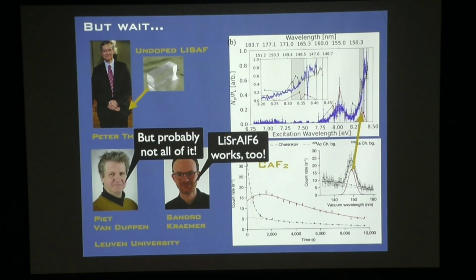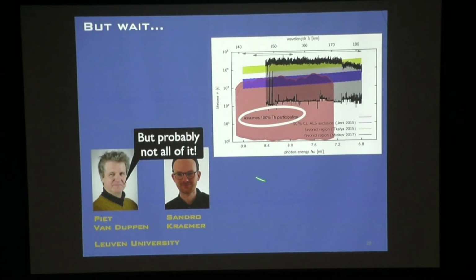And so this was a key realization for us. Because I had previously thought, well, if there's some quenching, maybe 1 in 10 to the 8 isn't quenched or something. Like the signal's sort of hopeless. If there's a little bit of quenching, it's probably all quenched, right? But they were saying, maybe a few percent actually survive and actually emit photons. And so this exclusion that I gave you, you have to pick something. So we always just said this assumes 100% thorium participation. So all the thorium in the crystal would contribute to the signal. If it's a percent, these move down by about 2 orders of magnitude. And so now some blue region is now allowed.